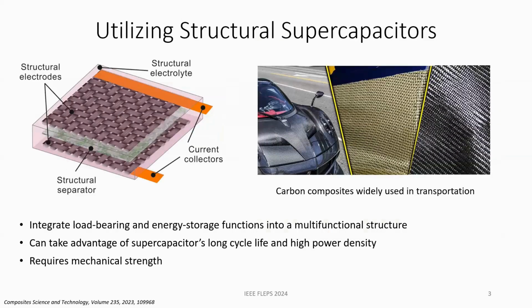So the way we decided to do this is by using structural supercapacitors. Structural supercapacitors integrate the load bearing and the energy storage components. So we increase the active material area by putting it in the hull of the device, and then we can also reduce the weight. When we look at cars and boats, they already use carbon composites for the same reason that we use it for our energy research. They're lightweight and very strong, so it's very easy to integrate these two together.